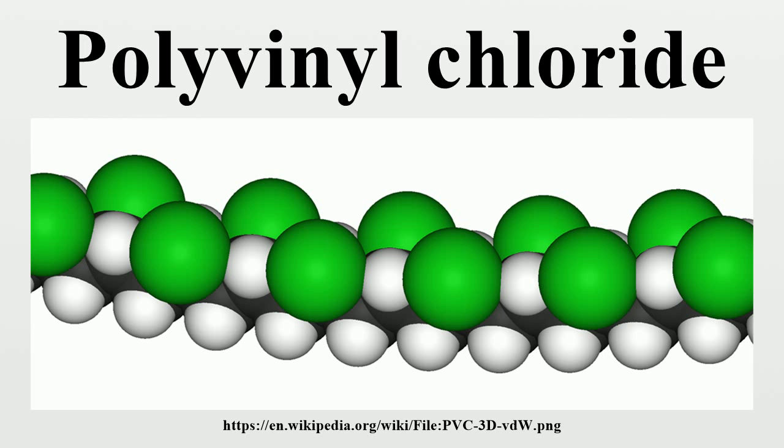The polymerization of VCM is started by compounds called initiators that are mixed into the droplets. These compounds break down to start the radical chain reaction. Typical initiators include dioctanoyl peroxide and dicetyl peroxydicarbonate, both of which have fragile O-O bonds. Some initiators start the reaction rapidly but decay quickly, and other initiators have the opposite effect. A combination of two different initiators is often used to give a uniform rate of polymerization.